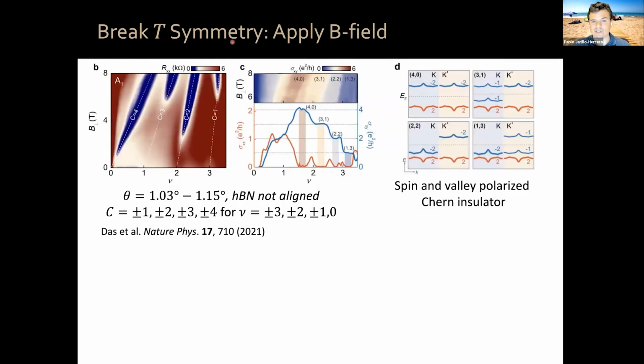Now, you can instead break time reversal symmetry. So by now, several groups have observed the existence of Chern insulator states in the presence of a finite magnetic field which stabilizes the Chern insulators, okay? And you can see a very interesting sequence of Chern insulators with Chern numbers 1, 2, 3, 4 at filling factors 3, 2, 1, 0, okay? Again, all of these 1, 2, 3, 4, etc. have to do with this 4 degrees of freedom, valley and spin, that I told you earlier. Yeah? You can do this in the presence of a finite magnetic field.